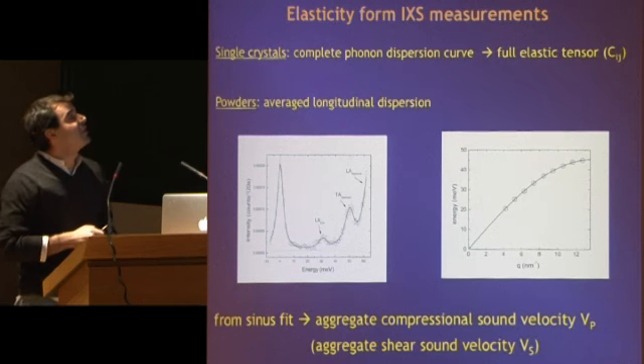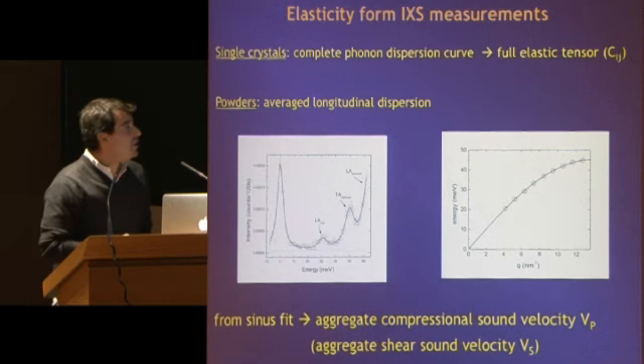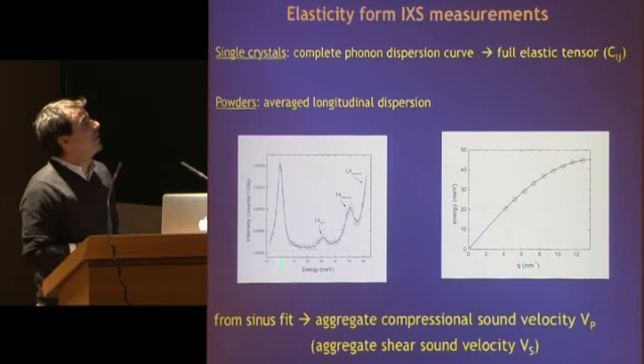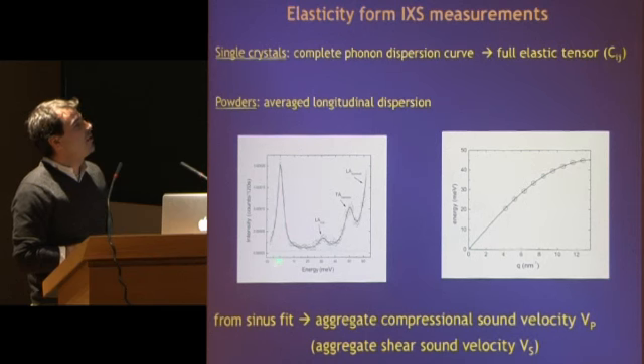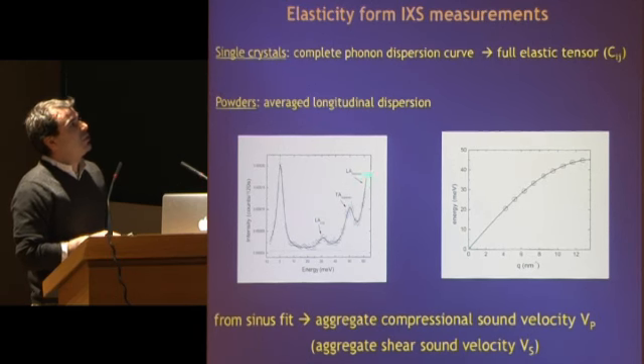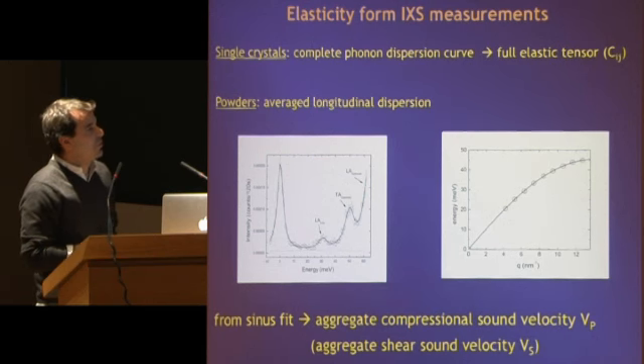And in the case of a polycrystalline sample, what is probed is an average longitudinal phonon dispersion. Here are examples of the raw data that are characterized by an elastic scattering at zero energy, a peak of the phonon excitation of the sample, in this case iron, and the two transverse and longitudinal phonon excitations of the diamond anvils.